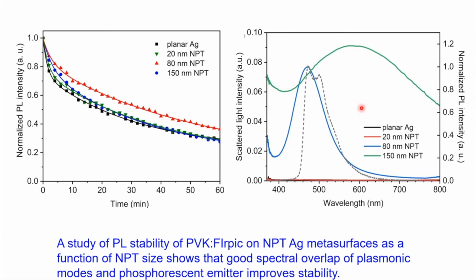We explain this by looking at the scattered light spectra of the different surfaces. If you can see, for the 80 nanometer case, the scattering spectrum overlaps very well with the emission spectrum of the phosphor. So clearly these two resonances can couple well because there's good spectral overlap between the 80 nanometer silver nanoparticles and the emission of that phosphor. For the larger nanoparticles, the surface plasmon resonance wavelength shifts to much longer wavelengths and is no longer resonant with the emission of the phosphor. And for those smaller nanoparticles, there's very weak localized surface plasmon resonance, so they don't show up at all in the scattering.